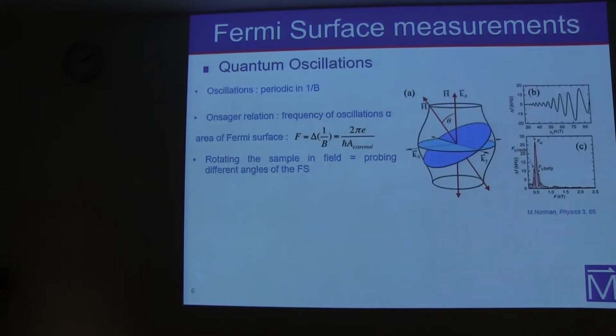So how can we characterize these quantum oscillations? The oscillations are periodic in 1 over the magnetic field. And the frequency of the oscillations is characterized by the Onsager relation. This Onsager relation links the frequency to the area of the Fermi surface that's mapped. For example, if you take a look at this standard Fermi surface, you have here one external area of the Fermi surface, but you can also have a neck that will give you a second frequency, which will give you the area of that neck.